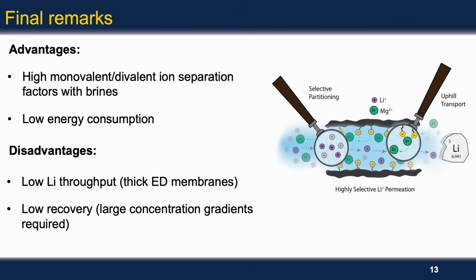I'll end this video with a couple of words on the advantages and disadvantages of this approach. One of the key advantages is the exceptionally high monovalent divalent separation factors, especially considering that we used realistic brines in the final experiments. Another advantage is the low energy consumption of concentration-driven processes, because the driving force for transport in this case is natural. Although this process will likely have to be combined with another technology like reverse osmosis, the separation is essentially low energy. The disadvantages are low lithium throughput.